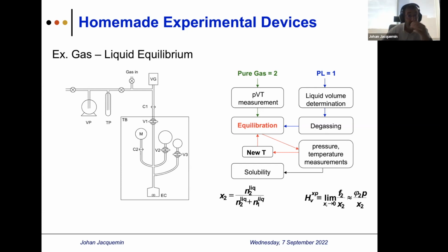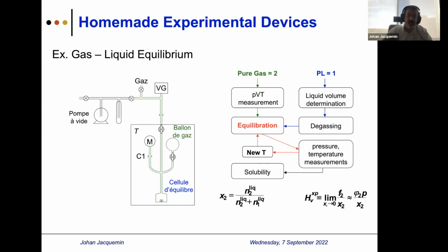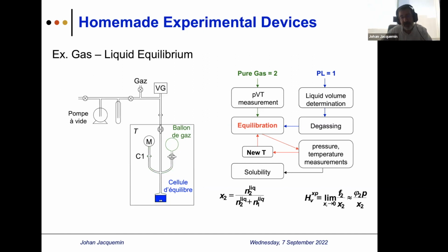The first step of any gas-liquid equilibrium, low pressure, I would say, gas solubility measurement, is you need first to trap a well-known quantity of gas in a well-calibrated gas bulb. And of course, to reach the equilibrium, you need to have a very well stabilized temperature within the whole equilibrium cell, and you need a very highly accurate manometer. Then when you reach equilibrium, if you have a non-dead-volume valve, I would say, you can determine the quantity that you trapped in the gas bulb.